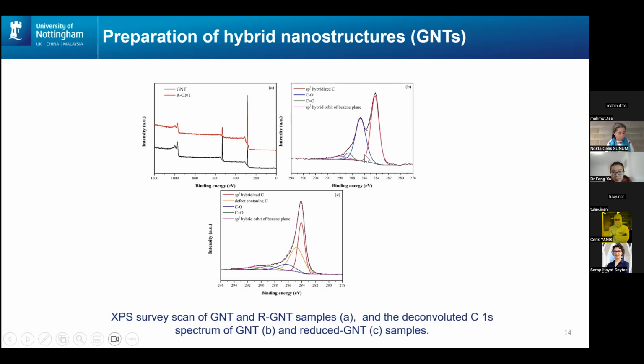If we compare B and C, we can note that the oxygen peak has been reduced. This is because those oxygen groups in graphene oxide have been removed. If we look at the survey scan or at B and C, we can notice that oxygen, this blue one and the green one, has been largely dropped because it's already been removed during the reduction process in hydrogen. So we can be confident we achieved the reduced graphene oxide and carbon nanotube structure.